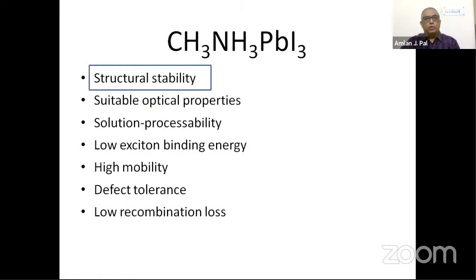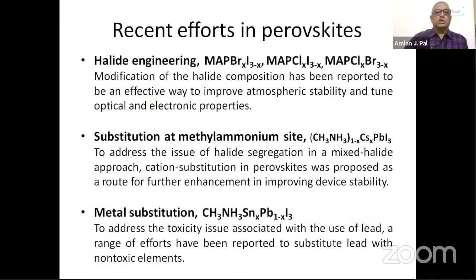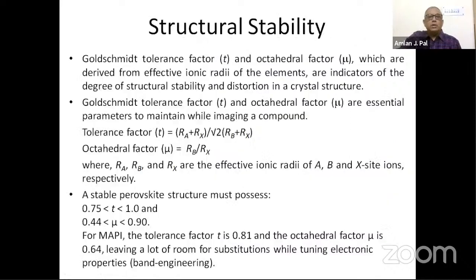So I will now go through one after the other quickly, how one can make this material and why this material has become so important. Structurally stable: you need band engineering because you need to change the material for many devices. Whatever you do, like halide engineering, meaning you play with the halogen site, or substitution at the methyl ammonium site, or even substitution at the lead site, you find that the material remains structurally stable. What factors do we look for when we check whether a material will be structurally stable? We look at the Goldschmidt tolerance factor or the octahedral factor, which are derived from the effective ionic radii of the elements. They are the indicators of whether the material is structurally stable or under distortion of the crystal structure.